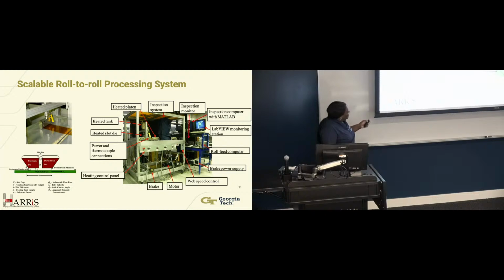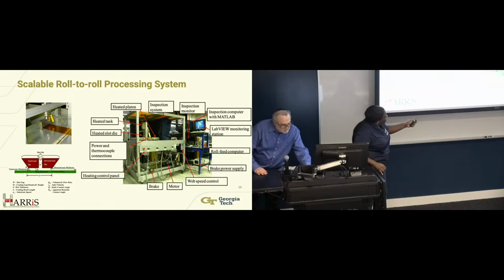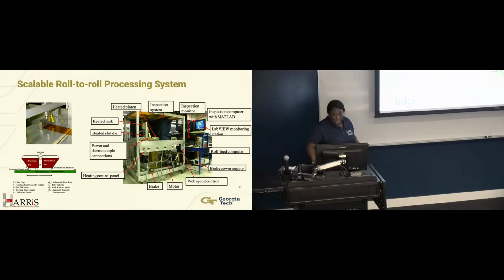Some of the nomenclature: this is the flow rate, so this is the fluid being pumped into the orifice. This is the standoff height. If you're looking at the base of that die, the standoff height, these are the contact angles that matter. Two are static, the two at the top, but the one at the base is dynamic because the fluid is literally moving up, forward and back, depending upon the flow rates. And then the substrate speed, U sub V, is the substrate itself moving. And so here, this is our substrate. It's pulled up, over, and it's taken up over here. And then we have the computer system to allow us to capture various images that you will see shortly.